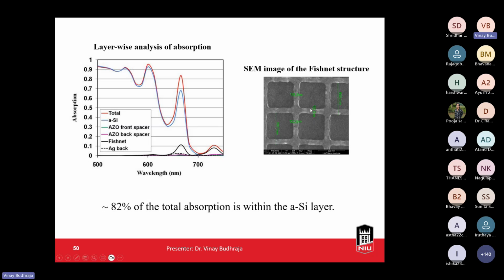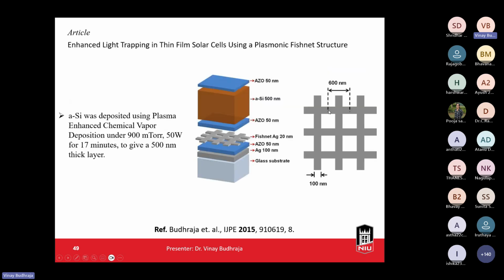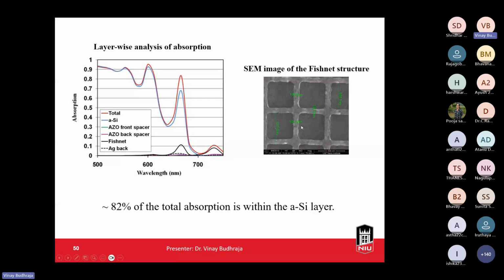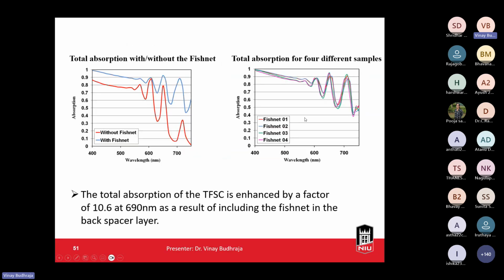And here is the SEM image of the fishnet structure. Earlier in the figure, I showed that it's 600 nanometer and 100 nanometer. So that's the same feature we got from the SEM. So these are the SEM images. Total absorption comparison with and without fishnet structure. With fishnet, it's clearly visible in the absorption measurement. With fishnet, the absorption increases, especially at around 700 nanometer.